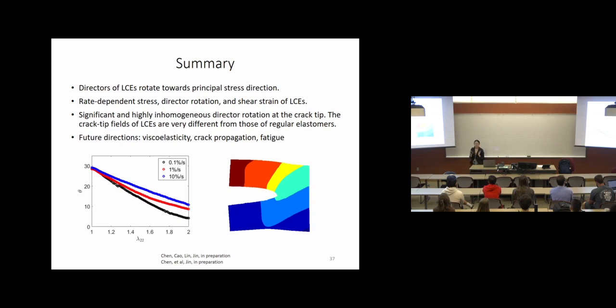I'm talking about the liquid crystal behavior. They show highly coupled stress-order fields. The director of liquid crystal elastomers can rotate towards a principal stress direction. And we also observe this highly rate-dependent stress, director rotation and the shear strain. And more interestingly, we study this crack tip field. We observe significant and highly inhomogeneous director rotation at the crack tip. And the crack tip fields of liquid crystal elastomers are very different from those of traditional rubbers.